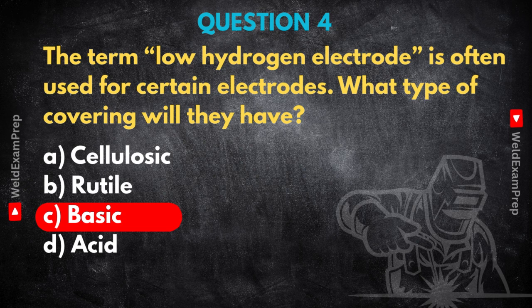If those basic electrodes absorb moisture from the air, they completely lose their low hydrogen property. When you weld with them, that moisture breaks down, releasing hydrogen straight into the weld pool. The immediate concern: hydrogen-induced cracking, delayed cracking. It might not show up right away, but it can cause catastrophic failure later, especially in high-strength steel.